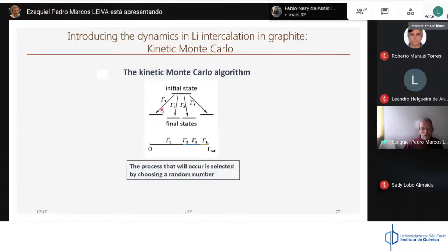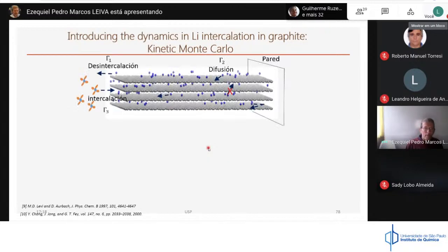The idea of kinetic Monte Carlo is very simple. You have a number of states and transitions. You have an initial state, you have different final states, and you calculate the probability, the rate, of the transition to the different states. And from these rates, you just throw a random number, and you choose a process to happen, and so you go on with the simulation. The nice thing is that when you use this kinetic Monte Carlo simulation, you can introduce realistic things, like the insertion. You remember that when you spoke about ordinary Monte Carlo, we had insertion everywhere in the system, but in realistic systems, you don't have insertion everywhere. You have only insertion at the interface, like here.